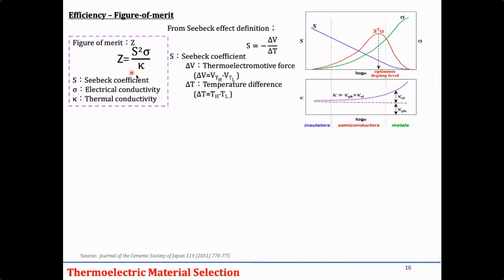And the third parameter is kappa. We again categorize kappa into two contributions: one is phonon and the other is electron. If you want to increase Z, we try to increase these two parameters, or we decrease this parameter. When we try to decrease the kappa parameter, we can increase Z.